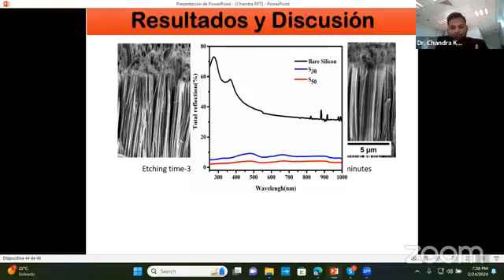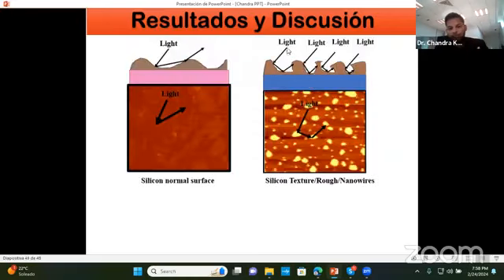The same we have observed here. See, when sunlight comes here, then due to multiple scattering, one strike here, second here, third here, and finally, after a lot of such interactions, light would be captured by that material. But in the case of flat, smooth, polished or normal silicon, sunlight comes and it could be absorbed. I'm not talking about total reflection, because silicon reflects 66% of light. This light might be either absorbed or transmitted. But when you complete the discussion of the mechanism, in the case of textured silicon, rough silicon, nanowire or porous silicon, due to multiple scattering, light could be absorbed.